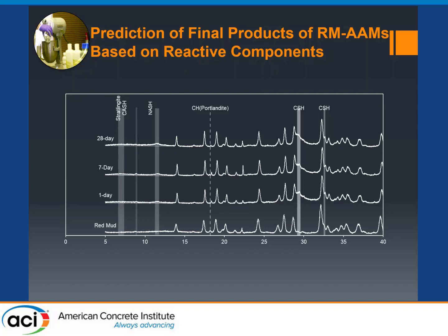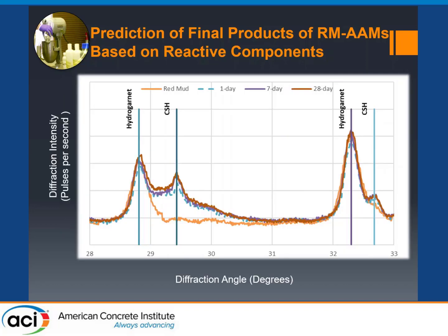For this sample, Red Mud concrete, the major hydration product is CSH. We have some minor CASH and NASH, but mostly CSH. As we can also see from here, the Red Mud generated a lot of CSH. Among them, hydrogarnet is a crystalline phase in Red Mud because it is very strong. Although it's not reactive, it can be used as a filler to provide high strength. So actually, it's very easy to achieve very high strength for Red Mud concrete, easily more than 100 megapascal.